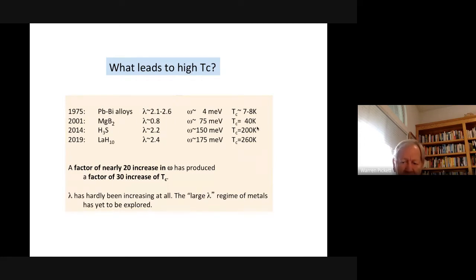But that's still controversial. Okay, but what we find here is that a factor of nearly 20 increase in the frequency, from here to here, has increased TC by a factor of 30, while lambda has hardly increased, or you could say hasn't increased at all. So the high TC that we've been seeing is all because the frequencies are getting higher, but we're retaining coupling. At least lambda's not decreasing. So lambda's hardly been increasing at all.